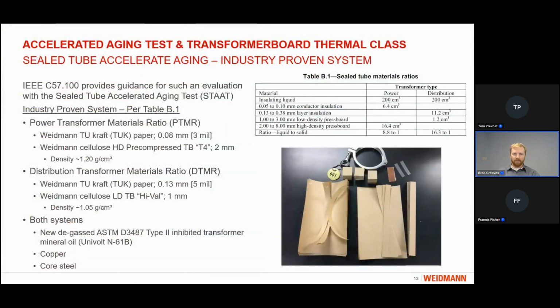First, when we look to determine how we can answer this question, we look to the IEEE C57.100 test standard. This test standard provides guidance for such an evaluation with the so-called sealed tube accelerated aging test. And within this test, we first look at the industry proven system. Looking at Table B1 within this test standard, we actually have two material ratios defined. First one being the power transformer materials ratio.